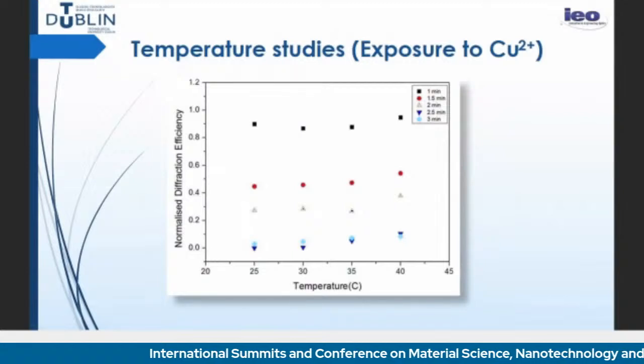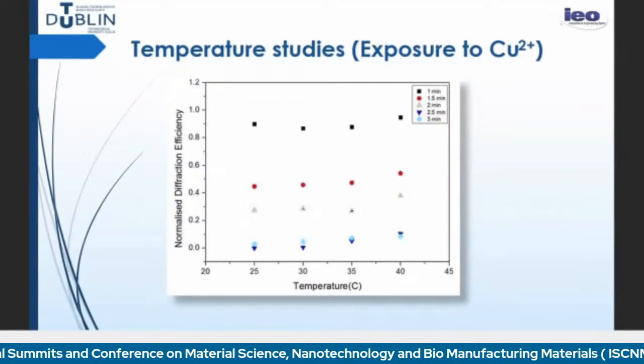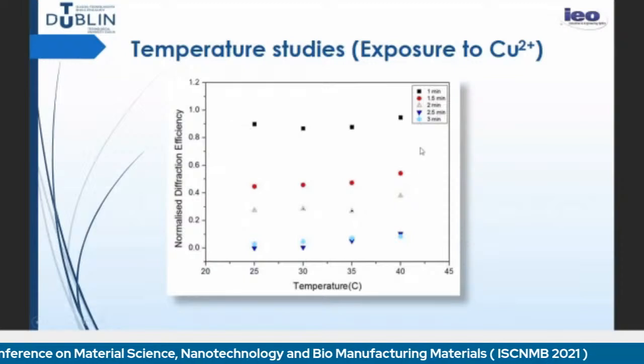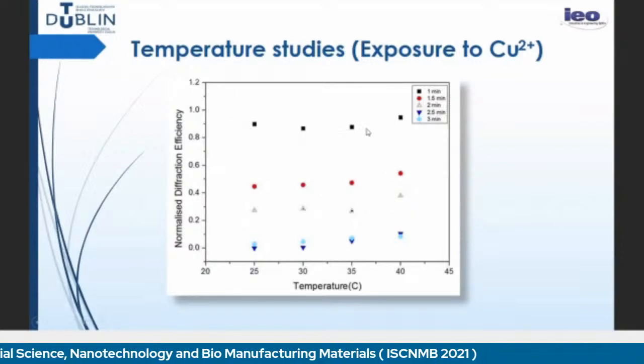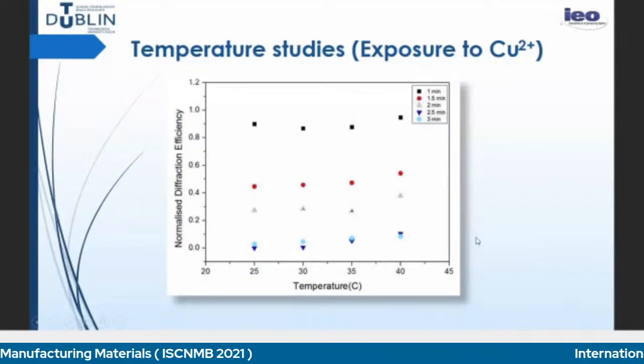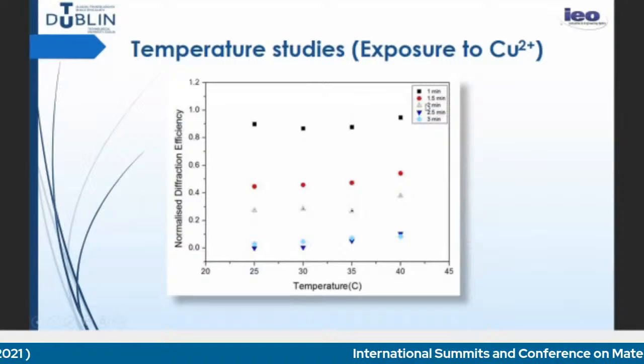So we have also tested to see whether our sensing is dependent on temperature, because this is very important. And up to 35 degrees, you see that there is not much change in the response with temperature. Of course, when you go to 40 degrees, then this should be corrected. Some correction factor should be introduced.